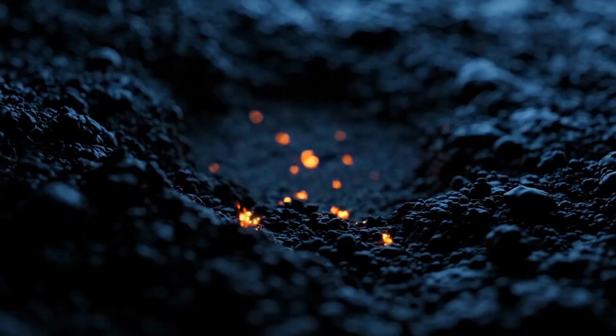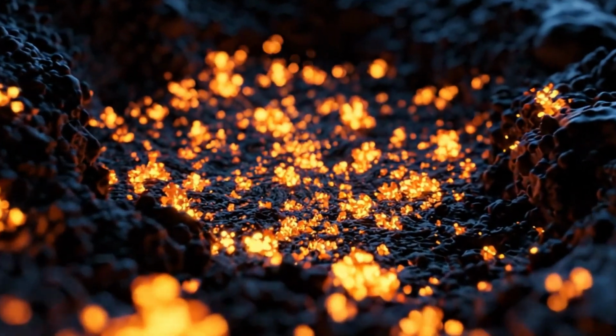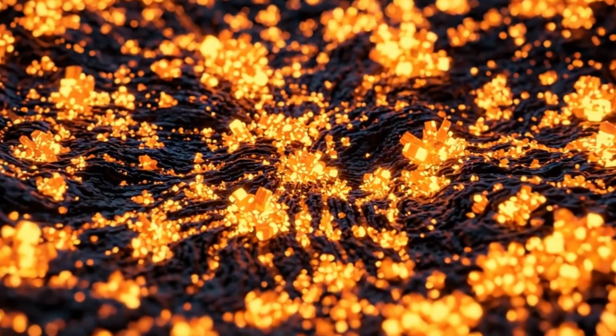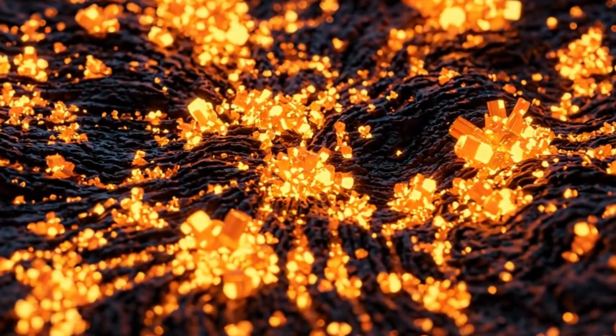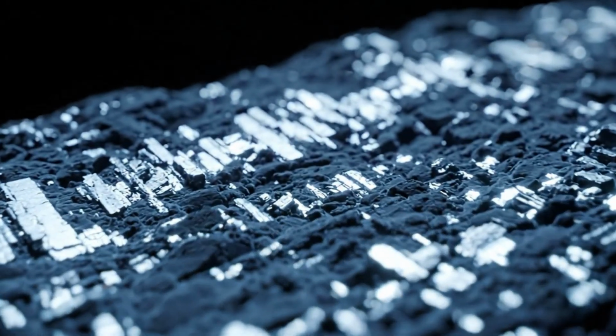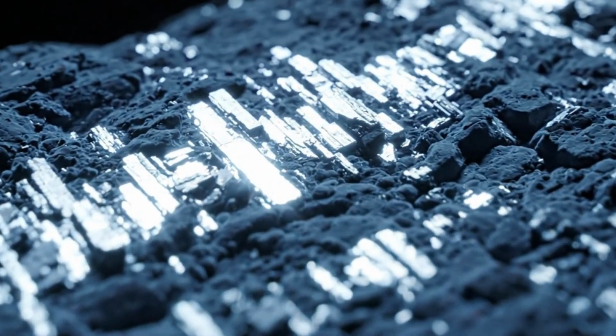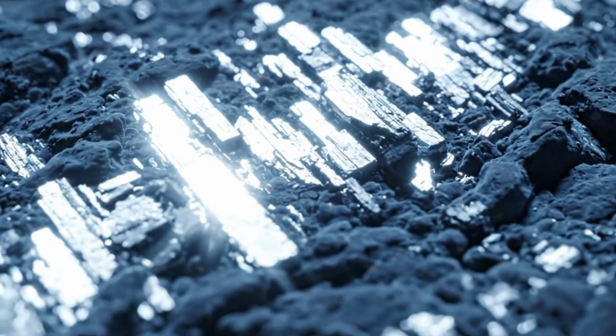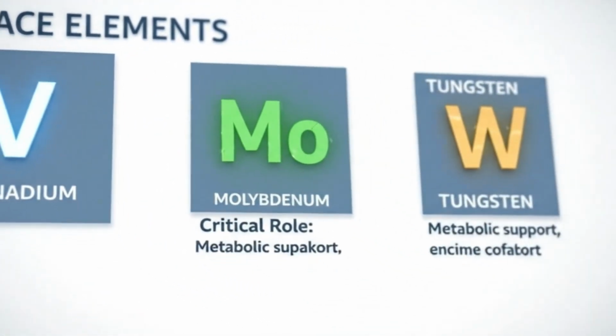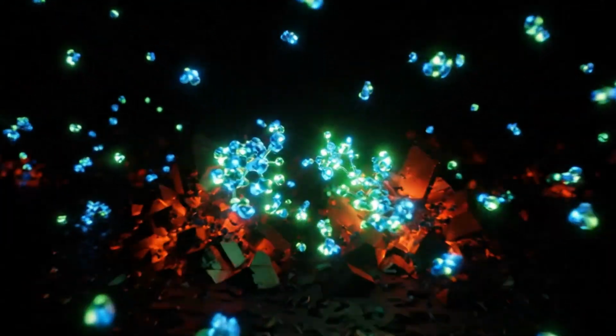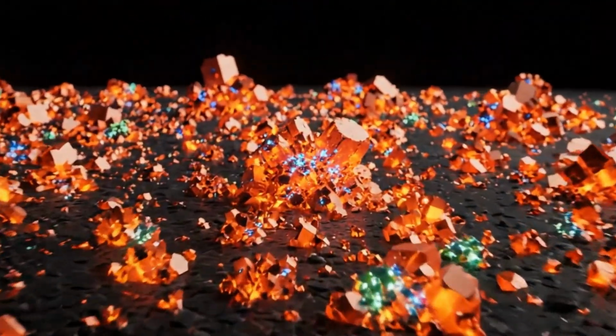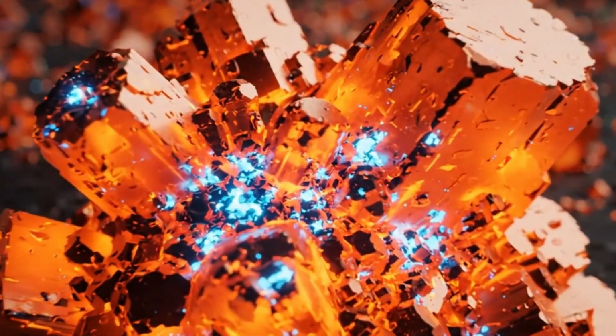However, such high carbon content usually makes steel brittle. The genius of the Wootz process lay in controlling the formation and distribution of these carbides, preventing them from forming large, continuous networks that would lead to brittleness. Instead, they formed fine, discontinuous bands that provided hardness while the surrounding ferrite offered toughness. The presence of trace elements like vanadium, molybdenum, and tungsten, often found in the specific Indian iron ores used, played a critical role in nucleating these carbide structures, influencing their size and distribution. This subtle interplay of chemistry and thermodynamics was the true secret of Wootz.